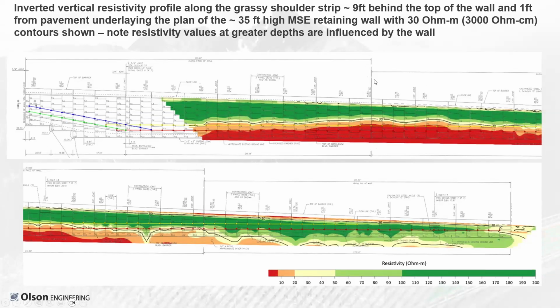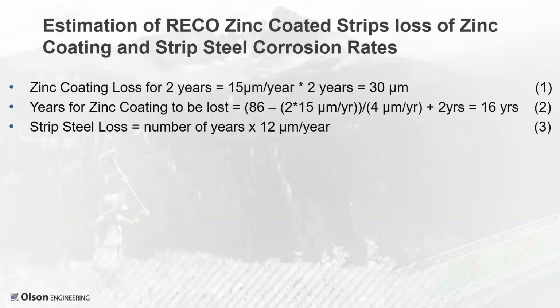And I think we succeeded there, where you can see on this bottom plot a little bit better. We have at the very tops of the soils, we have a much more resistive medium before getting to a much more conductive medium, red, relating to more corrosive material, compared to deeper where it might be more sound. So I'm going to pass it back to Larry to talk about our estimations for using that corrosive data for lifespan left within these strips.